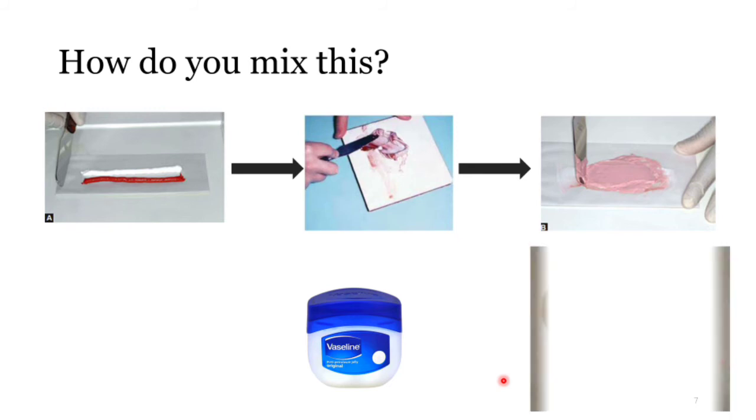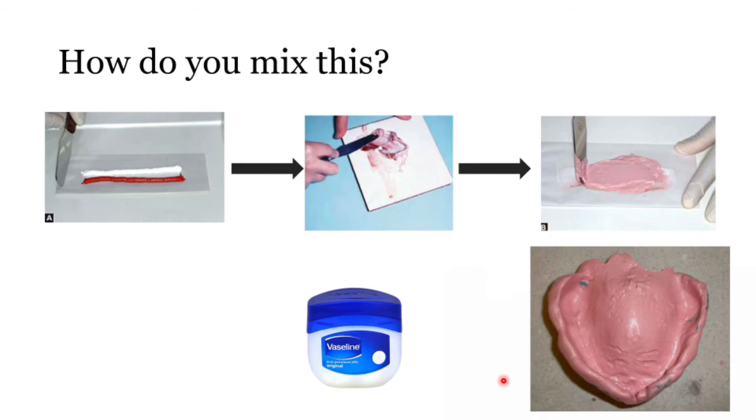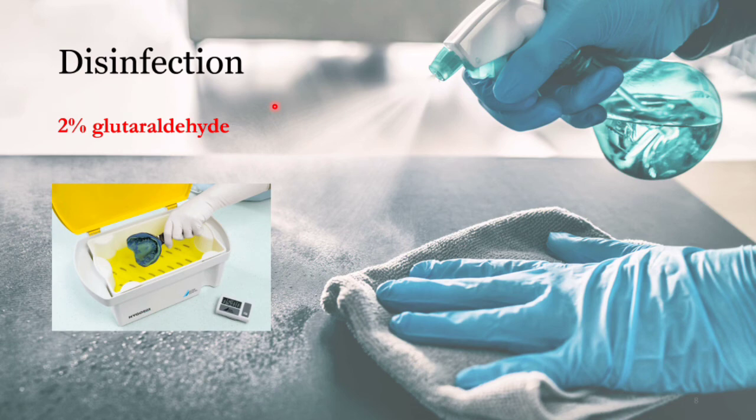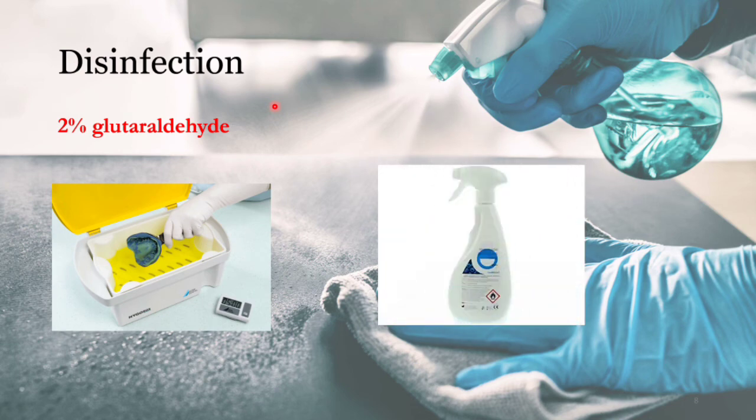How to disinfect such impressions: As I told you in the previous video, you should disinfect the impression or the cast, especially during a pandemic. Disinfection is one of the important parameters for dental setups, students, practicing dentists, and lab technicians. Two percent glutaraldehyde is used for disinfecting impressions. Two methods exist: immerse it in the solution, rinse, and keep it out, or spray the disinfectant. For zinc oxide eugenol paste, the immersion or rinsing type is better.